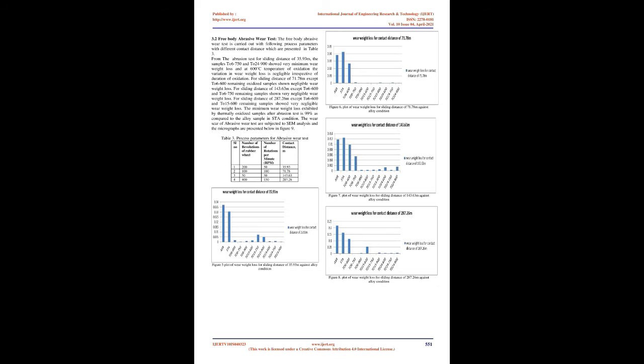2.2 Abrasive wear test. Abrasive wear test was carried out on a sample of rectangular plate of 25 mm, 75 mm, 10 mm thickness prepared as per ASTM standard by fixing the sample in the specimen holder of Ducom dry abrasion tester, and the test is carried out with the process parameters explained below. Abrasion tests were carried out on Ducom dry abrasion tester, TR50, equipment as per ASTM G65 standard with the